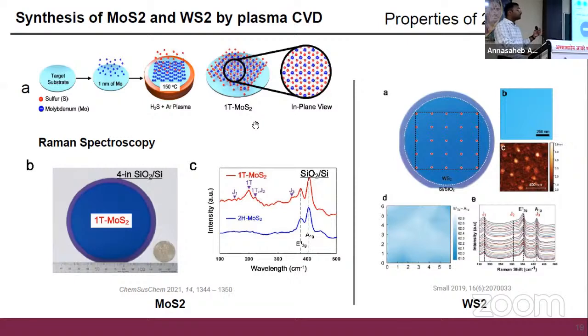As we have found out, the dominant phase in our synthesized material is 1T along with 2H. That's why we are calling it 1T MoS2, since almost 70 to 80% of the phase is 1T phase.